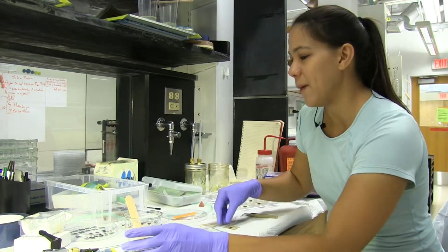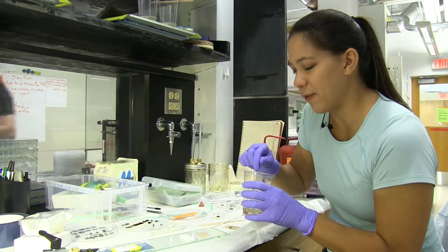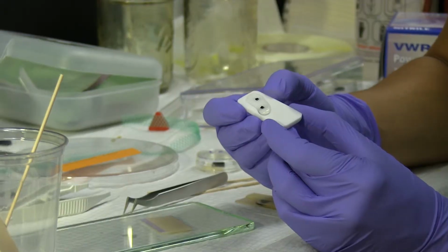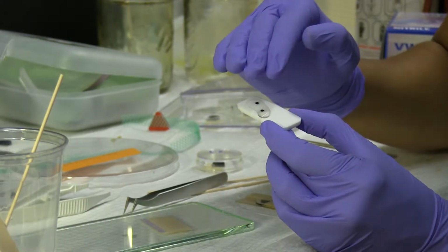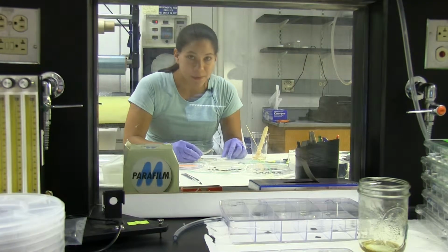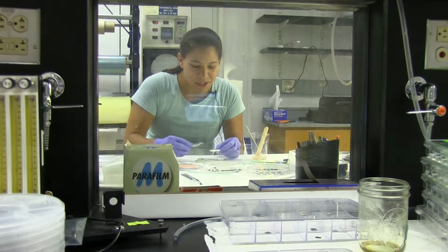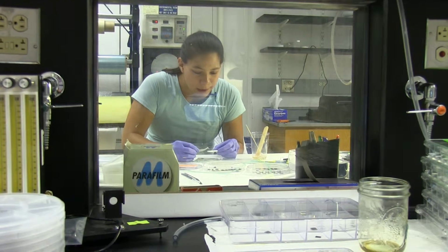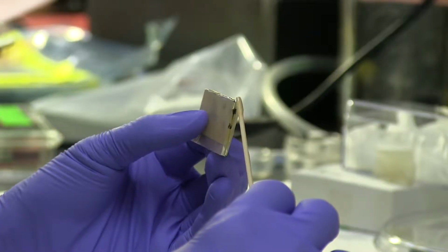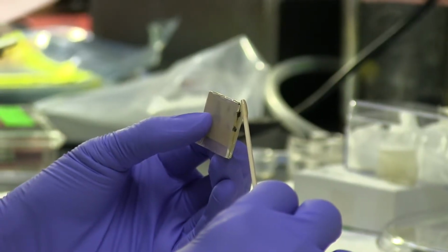So I'm looking at how my small nanotube forests interact with polymer. As you can see, it was resting on top of this epoxy pile, but now it's sinking deeper into the pool. Just as a last step, what I'm going to do is transfer these to a different surface so that I can actually sandwich them between 2 stiff plates to force them to lie flat as I cure.